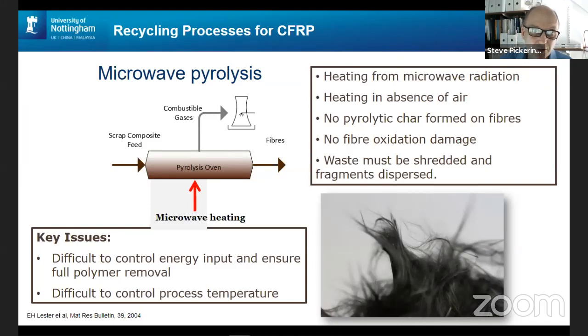And similarly, because you're in the absence of air, there's no fiber oxidation damage at all. There's no oxygen there at all, so you're not going to get any oxidation damage. But you'd need to shred the materials fairly uniformly and have dispersed fragments going through the process for the microwave process to work properly. And I think the difficult issues in microwave pyrolysis are really the difficulty in controlling the energy input to ensure full polymer removal.